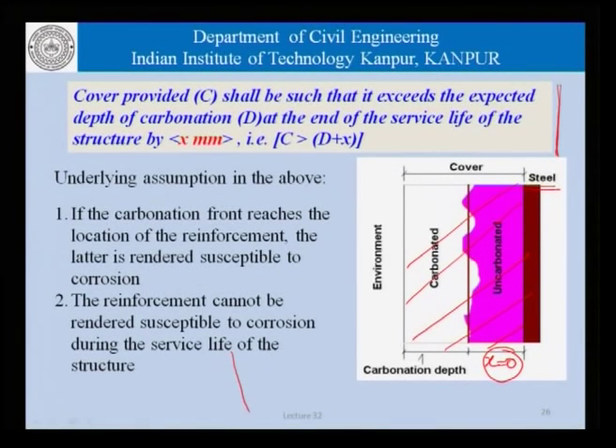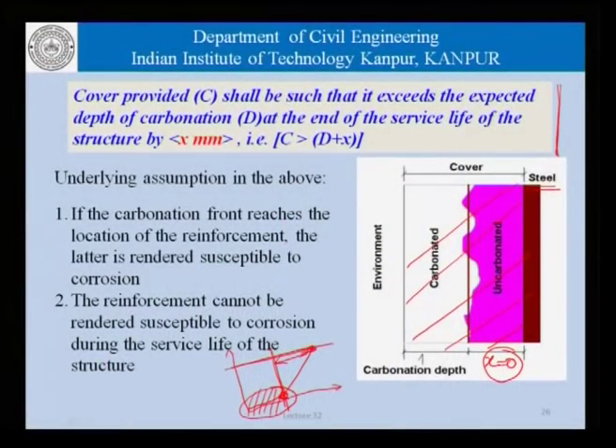In fact, if we look at models which talk in terms of service life of reinforced concrete structures and reinforcement corrosion, very often we see a model which is something like this, which says that this is the life during which no corrosion takes place, and beyond this point the corrosion is initiated here and reaches a point here which leads to formation of cracks. We have talked about this when we were talking in terms of the corrosion process within concrete and the deposition of corrosion products on the reinforcing bars and so on. In this discussion here, we are simply ignoring this part. We are saying that, well, our service life is confined to only the portion where the reinforcement is not rendered susceptible to corrosion. Whether or not corrosion occurs, what is the rate at which the corrosion will occur, those are some things which we are not talking about.